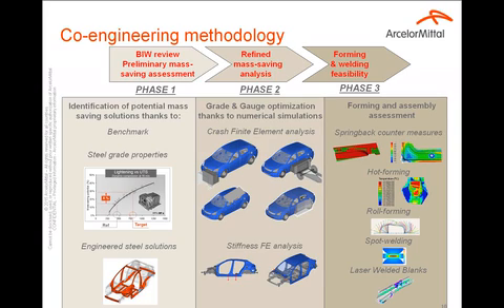The phase two is what we call the refined mass saving analysis based on grade and gauge optimization done mainly by numerical simulations. And phase 3 is the forming and welding feasibility assessment, where we can test different or resolve different issues regarding spring back, hot stamping, roll forming, spot welding, or laser welded blank.